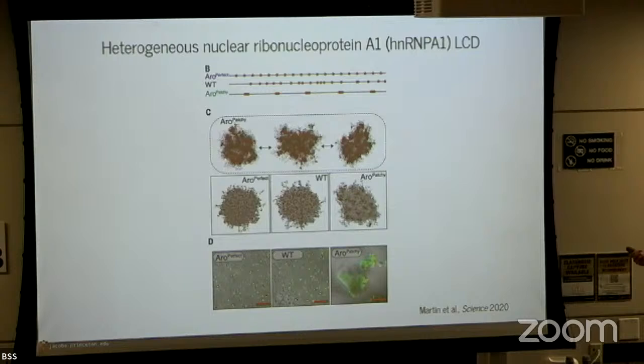And indeed, that's what happens. You end up in a region of your phase diagram where, for this patchy sequence, you no longer have fluid droplets. They're not spherical anymore, which indicates that you don't have a significant surface tension trying to form these droplets. Instead, it looks much more like a system-spanning network of essentially these cross-linked polymers. So this is a nice demonstration of what happens when you move from the weak binding regime to the strong binding regime just by scrambling the sequence.